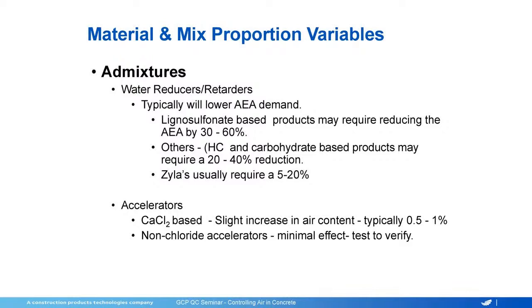So we don't want those all going in at the same time. We prefer to see the air entrainment dosed onto the sand. We realize that's not always possible, but if you're using hot water, you're using non-chloride, then you want to keep those separate from when the air goes in. And the best sequence, we internally have a recommended sequence of how the products go in, but it doesn't work for everyone because plants are all different, mixers are all different, how the materials are delivered to the mixer is different. So we try to work with our customers to help them determine the best material sequencing that will give them the most consistent air.